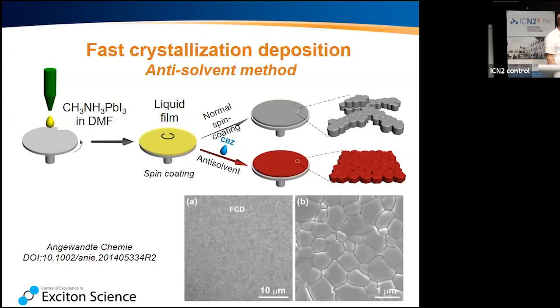With the anti-solvent method, while you're spinning your perovskite precursor, before it dries, you come in with chlorobenzene. Yesterday we had a talk about that, and you need to get the timing right. Yesterday we learned that if you have DMSO in your precursor solution, you don't have to be too strict on the timing. If you don't have DMSO, you need to be absolutely accurate, otherwise you take big losses.